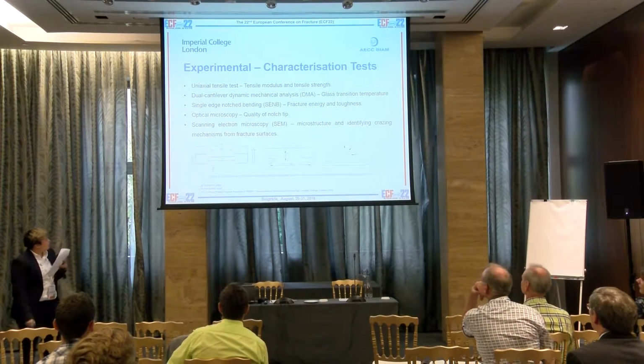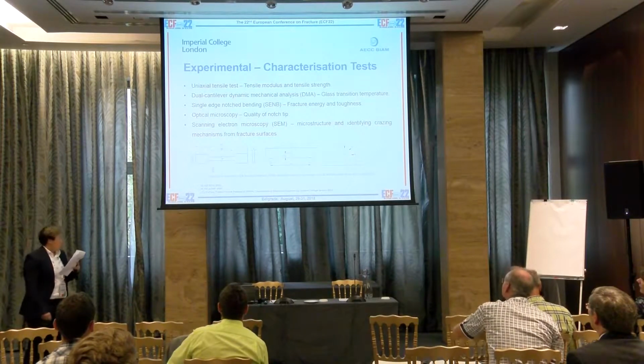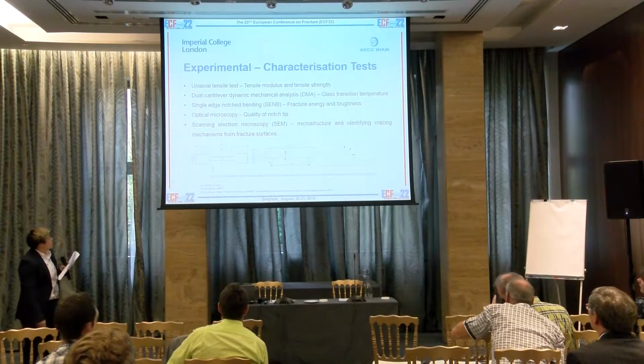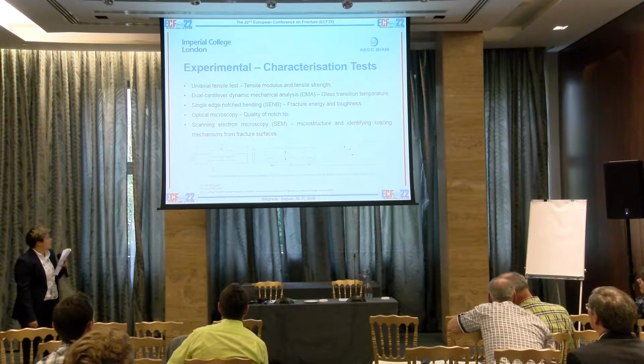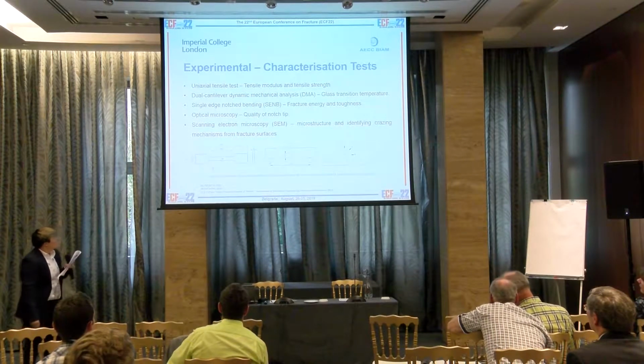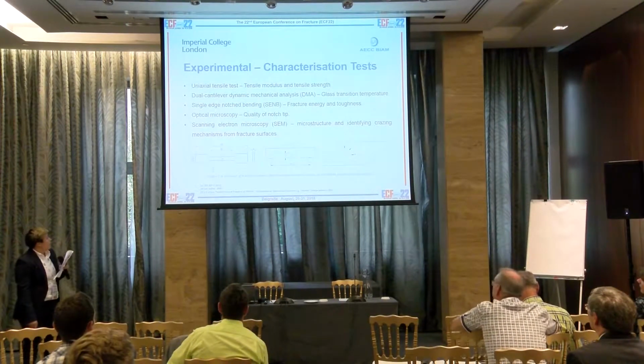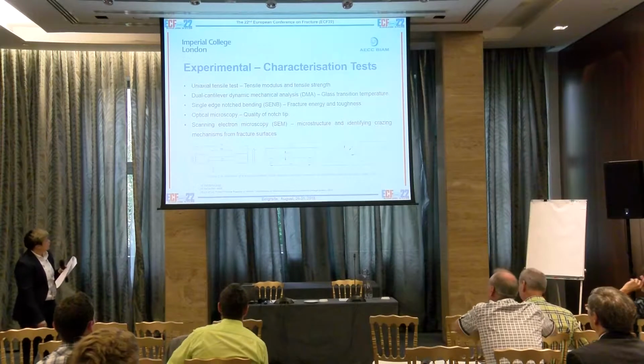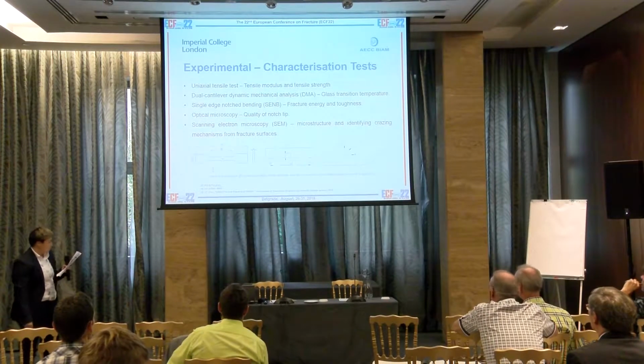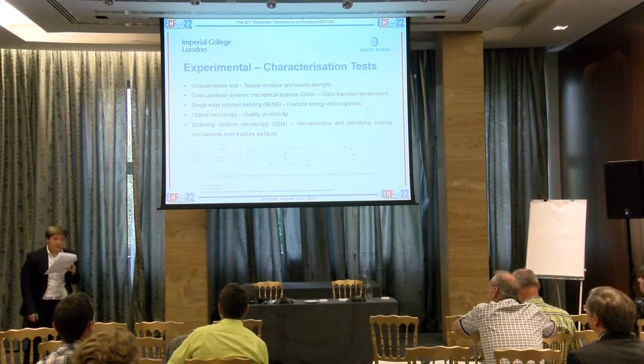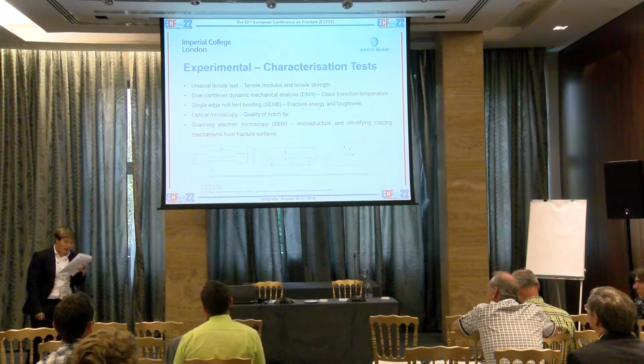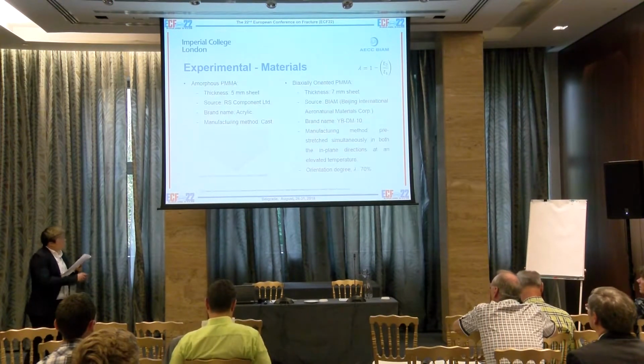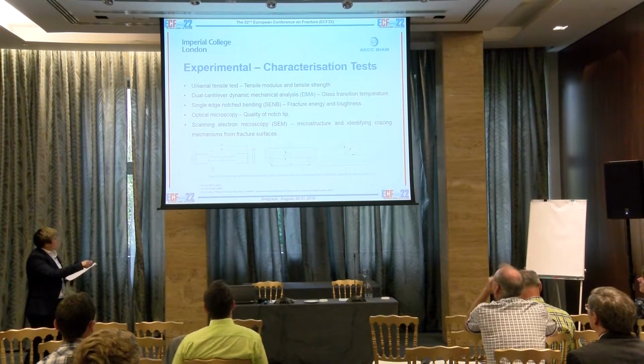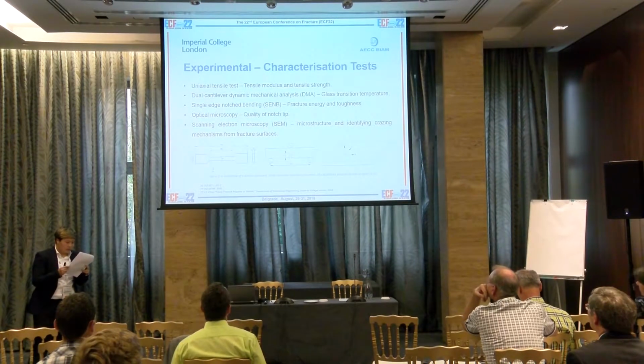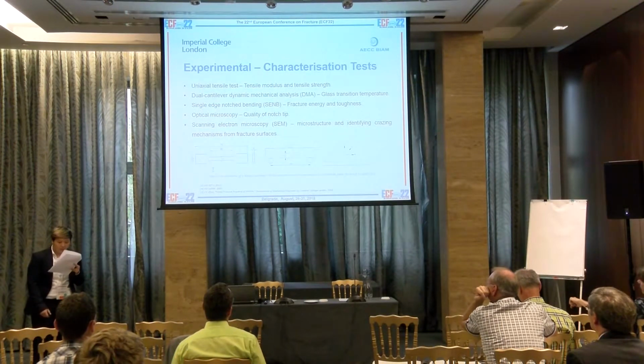So here are the characterization tests I did. Uniaxial tensile tests were done to calculate the tensile modulus and tensile strength of the polymers. Dual cantilever dynamic mechanical analysis, DMA, tests were used to determine the glass transition temperature. 3-point bending tests were performed on single-edge notch bending, SENB, specimens, which is this here, to determine the fracture properties.